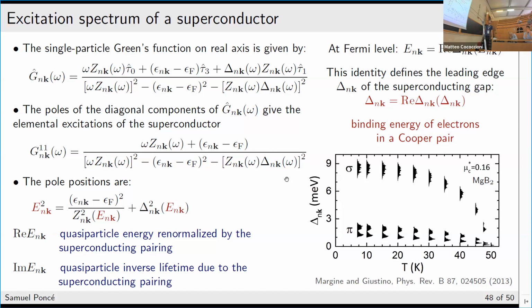Now, what is also interesting is that here, this is MgB2, and it's actually a multi-gap superconductor. So you can see that you have two band gaps, and the two band gaps are on different parts of the Fermi surface. So the Fermi surface is quite complicated. You have this sort of tubular structure, and one of the gaps is in one, and the other is in the other one. And so if you want to be able to describe things like MgB2, you really need an anisotropic description of the gap. Otherwise, you cannot really have only one gap that describes this two-gap structure.